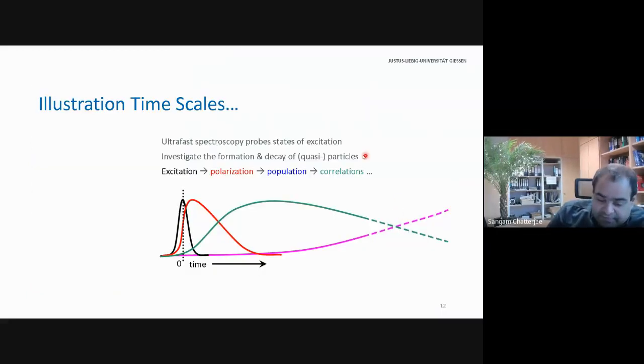And these things we look at on very different timescales. And here I go back to Maxwell's equations again. One colloquially says we excite electrons, but if we look in Maxwell's equations, we actually find there is no electron in there, even if we include matter. But what is in there is a polarization. So what we have is we come in with an electromagnetic field and we excite a polarization. The polarization is something you can Taylor expand, which leads you to the linear susceptibility and the higher order susceptibilities. But it's still a polarization, and you need some kind of scattering mechanism for an actual population to occur.